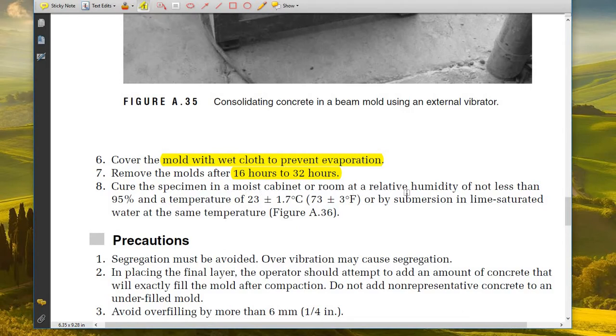Cure the specimen in a moist cabinet or room at a relative humidity of not less than 95% at a temperature of 23°C, or by submerging in lime-saturated water at the same temperature. We should put it in a container filled with lime-saturated water at the same temperature.